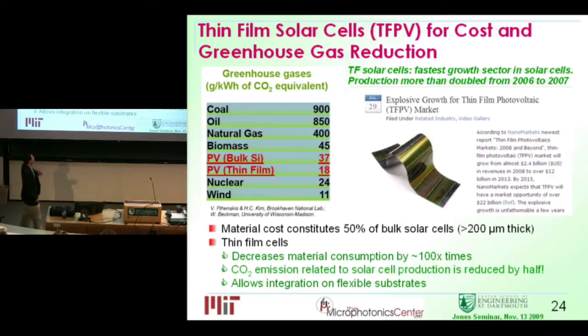Okay, so talking about reducing the cost, one way is thin film solar cells, because currently most solar cells use bulk material that's usually wafer level, 200 to 300 microns thick. If we reduce the material consumption with thin film solar cells, then we'll remove 50% of the bulk silicon cost. That is, we'll cut the cost at least by half. And there is additional gain in processing cost, because to get this bulk silicon, you need a very hot furnace, above 1,000 degrees. While doing thin films, you can use plasma-enhanced chemical vapor deposition. It's the same tool, same technique used in flat panel displays, a very mature technology, and potentially very low cost.